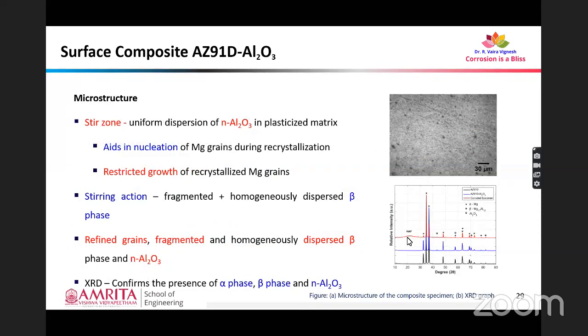So here I have shown the microstructure of the fabricated surface composite. In this, we have a stir zone in which we have a uniform dispersion of nano phase alumina in the plasticized matrix. This happened because this nano phase alumina aids in nucleation of magnesium grains during recrystallization, and it restricted the growth of recrystallized magnesium grains. The stirring action of the FSP tool resulted in fragmentation and homogeneous dispersion of beta phase particles. So cumulatively, we have obtained refined grains, fragmented and homogeneously dispersed beta phase and nano phase alumina in the fabricated surface composite. To confirm the presence of nano phase alumina, we have subjected the material to XRD analysis. The XRD analysis confirms the presence of alpha phase, beta phase and nano phase alumina as shown in the graph over here.